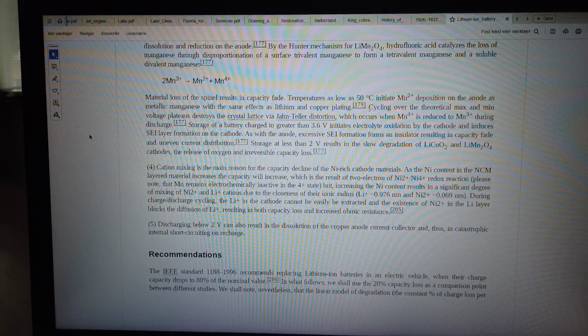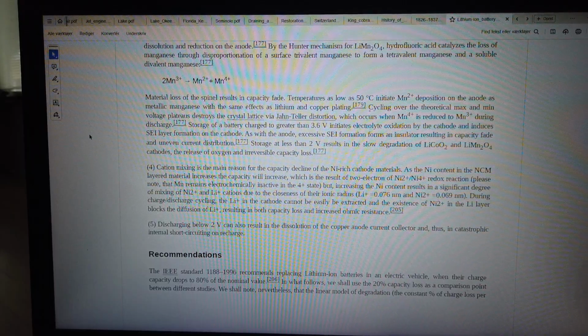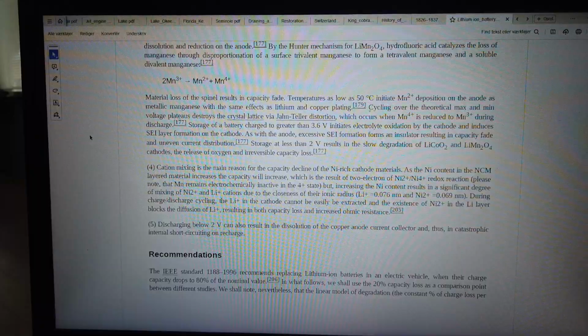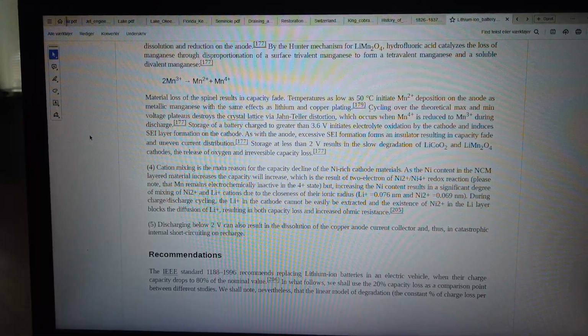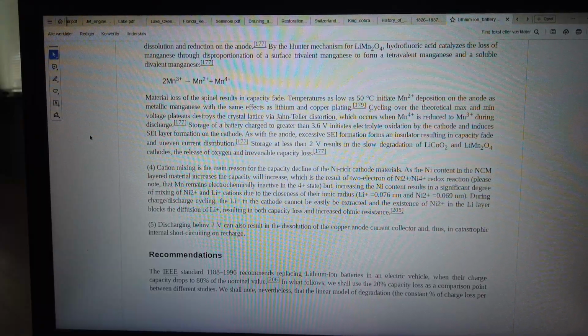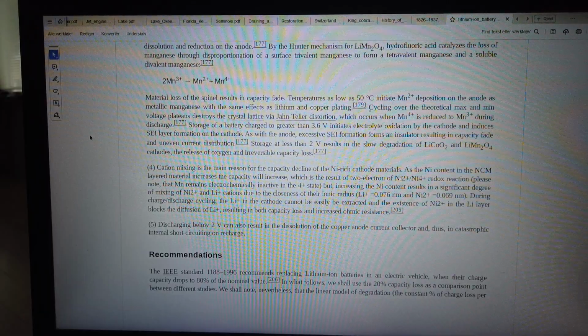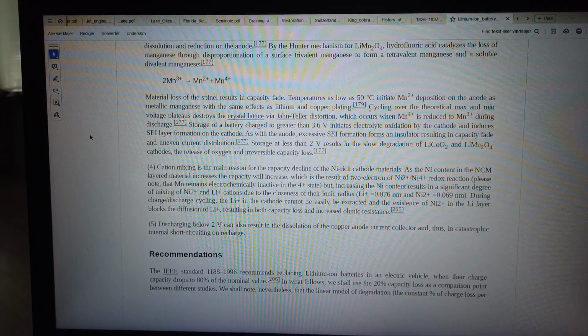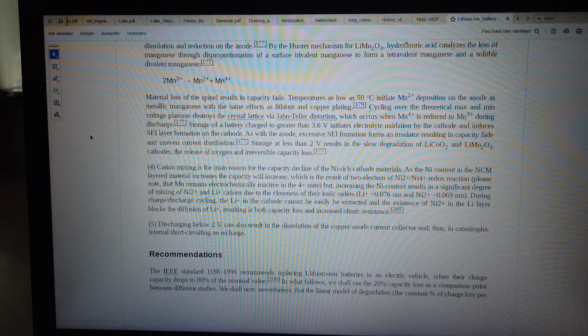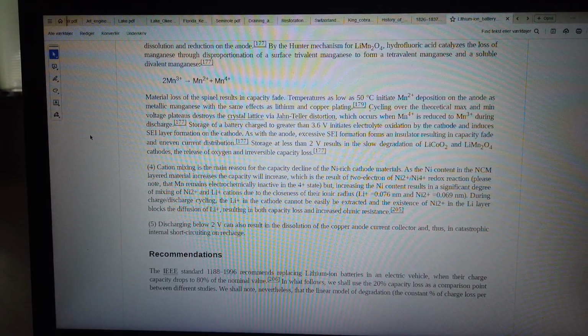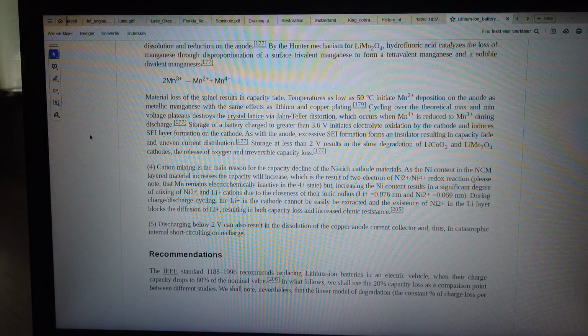As with the anode, excessive SEI formation forms an insulator resulting in capacity fade and uneven current distribution. Storage at less than 2 V results in the slow degradation of LiCoO2 and LiMn2O4 cathodes, the release of oxygen and irreversible capacity loss.